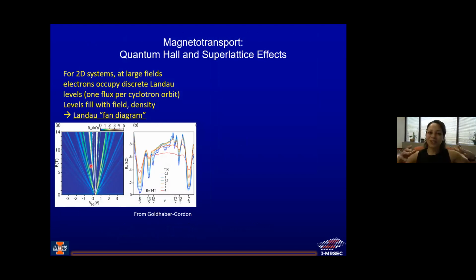Okay, so for 2D systems in magnetic fields, electrons have cyclotron motion, right? Electrons move perpendicular to a magnetic field and they just go around in a circle, okay? So the quantum Hall effect is basically when you have one flux trapped in a cyclotron orbit and all of these orbits basically condense into a ground state. Okay, so these Landau levels will fill with electrons, and the filling of these levels will vary both with magnetic field, because you can fill more flux lines per magnetic field, and also with electron density, because you can fill more electrons with more electron density.